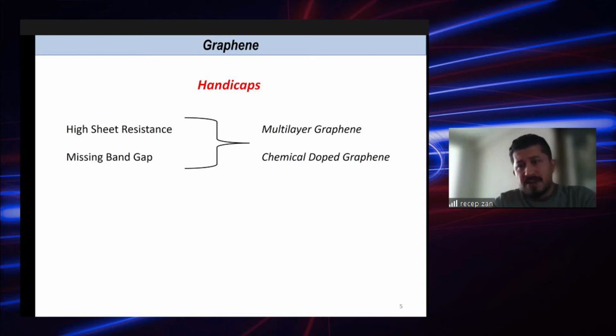Multi-layer graphene is easier to fabricate or obtain, but as you get thicker, you get a rather graphite structure rather than graphene. So chemical doping is much preferable. But let me emphasize, when we talk about chemical doping, we would like to keep the structure of the graphene, in the carbon structure, replacing carbon with impurities like boron or nitrogen.